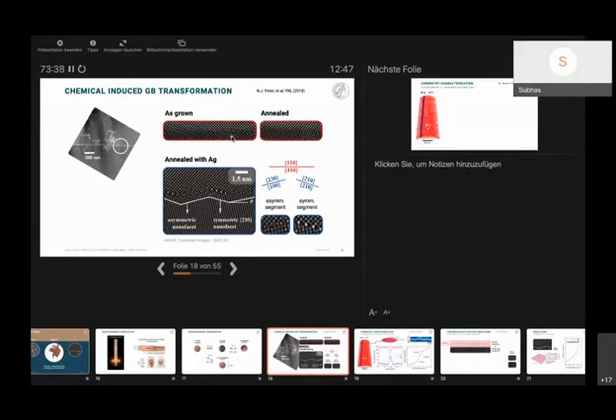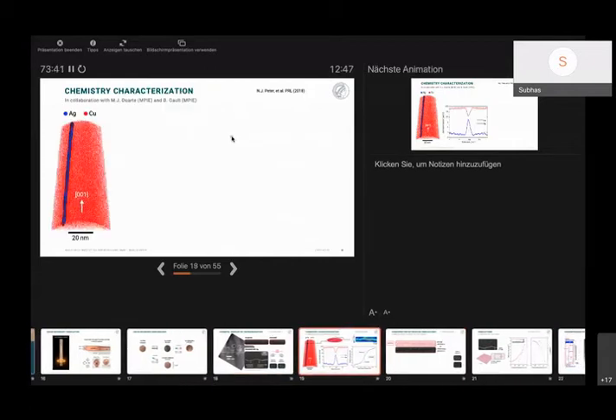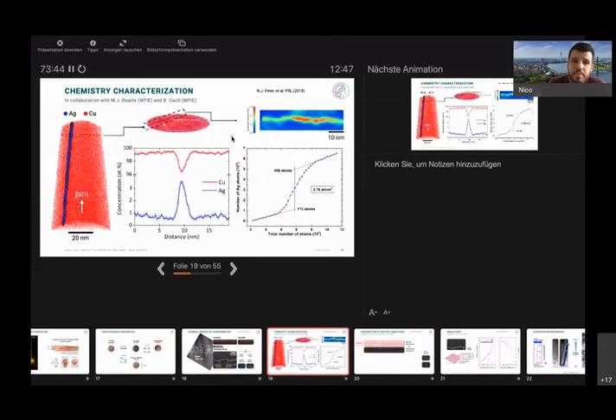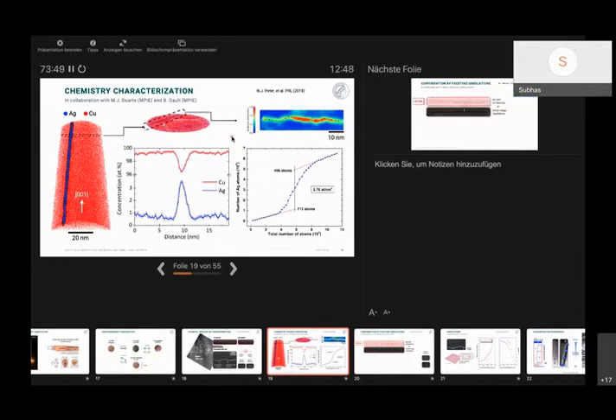And in the next slide, this 2D profile of this faceted grain boundary that you're showing. In this image, it's showing that in the asymmetric boundary also there is a concentration of silver. This in here you mean? Yeah, here. Even for higher sections, meaning this flat section or coherent sections or symmetric sections, it's not showing the concentration. You're a very good observer.